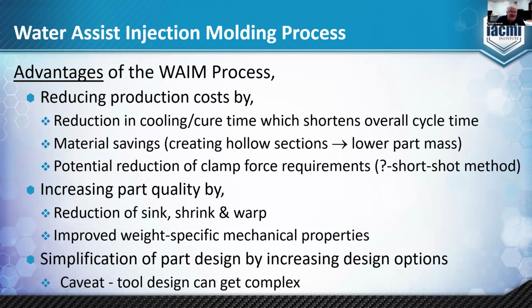So the advantages of water assist are a reduction in your cooling time, your cure time, which can shorten your overall cycle time. You have a material savings because you're creating hollow sections, and you have the potential to reduce clamp force, particularly if you use the short shot method with the water assist approach. I'll talk more about the short shot method in a few slides. You increase part quality by reducing sink, shrink, and warp, particularly warp if you're able to uniformly distribute the residual stress in the part over the entire part. And you improve the weight-specific mechanical properties because you are hollowing sections and creating geometric stiffness.